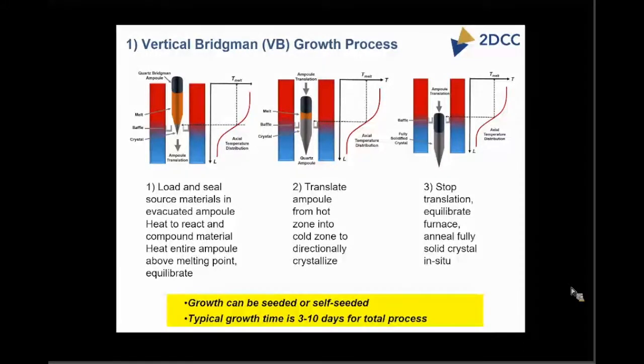And as I mentioned, the growth can be seeded or self-seeded. And the bottom line for crystal growth using the Bridgman technique is you have to be patient, because it often takes many days to grow crystals. A typical time for crystals of this size with these materials would be between 3 to 10 days. And I guess that really limits the number of runs you can do and the time that it takes to go through this process.